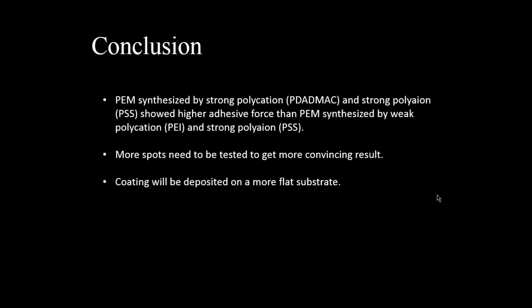To summarize, the PEM synthesized by strong polycations and strong polyanions showed higher adhesive force than PEM synthesized by weak polycations and strong polyanions. But in this experiment, we only tested two spots on the substrate. To get more convincing results, we need to test more spots and collect more data.